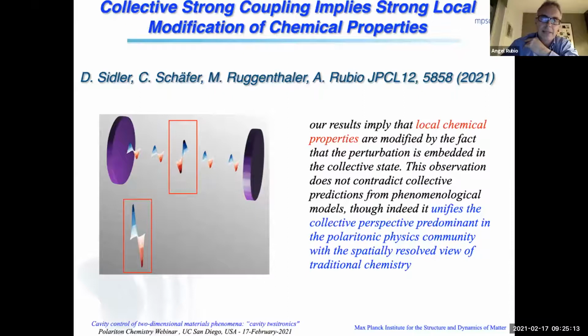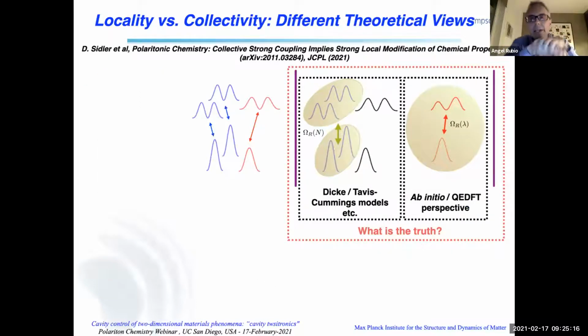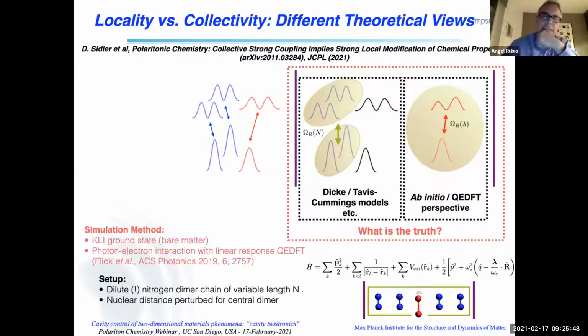Let me build a little bit more on that. And the question is, what do you have? If you have a set of dipoles that are coupled by a photon, you get this lower and upper polariton, which is the Tavis-Cummings model for interacting n dipoles. And the question is, if we do it in a more ab initio framework, what do we get? Are we able to reproduce this regime, or do we have something intermediate? Then whether we go to this macroscopic collectivity, or it is more the local nature of the interactions.